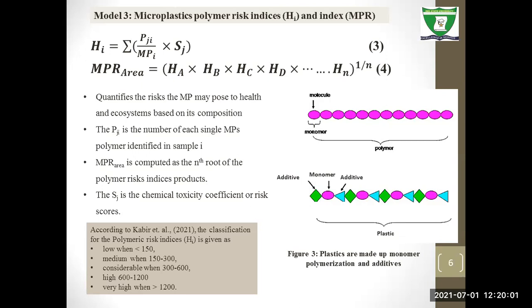Okay. Go ahead. So, like I'm saying, equation 3 is for the microplastic polymer risk indices, which is based on an individual sample. If you have, for example, a particular sample and the number of microplastics identified in that sample is 10, and among this quantity you have different polymer types, for example PP, PET, PVC, etc. So now the HI in equation 3, the polymer risk index, is the quantity of each polymer type, that is PJI, divided by the total number of microplastics identified in that particular sample.